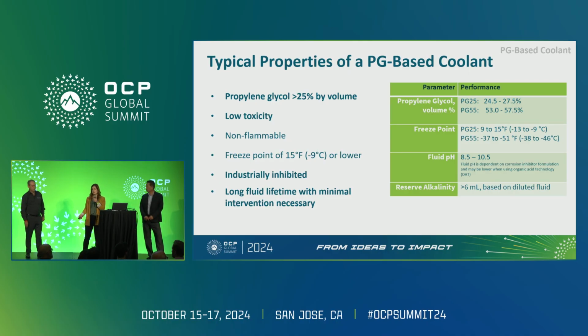You should achieve freeze points of 15 degrees Fahrenheit or lower, depending on the concentration you use. And then they should be industrial inhibited. So this means that they contain additives and inhibitors that are going to protect, most importantly, the metals in the system, but also prevent any issues with drops in pH and stuff like that. Last but not least, you would expect a long fluid lifetime from an inhibited PG-based fluid, with minimal intervention necessary. So you're not going to have to make adjustments to it routinely. It's going to be pretty straightforward maintenance.